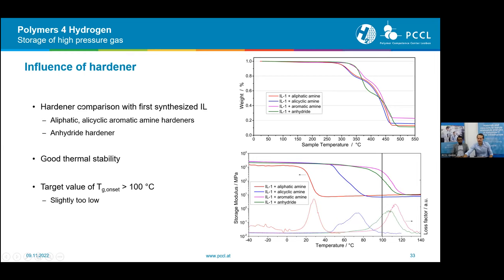So here we have our first synthesized epoxy ionic liquid. We did a comparison of different hardeners: aliphatic amine, alicyclic amine, and aromatic amine, and also one anhydride hardener. On the right, you can see that we once again reach very good thermal stabilities in the thermogravimetric analysis. And in the dynamic mechanical analysis, our goal for the glass transition temperature would be 100 degrees Celsius for the onset temperature. You can see that we are slightly below this, even for the aromatic amine and the anhydride hardener. So we had to change the resin a bit.